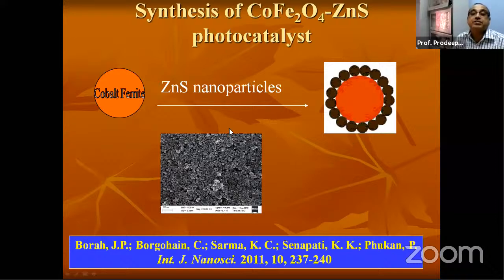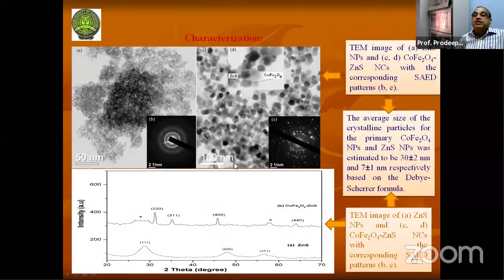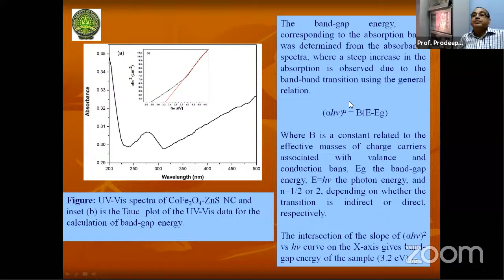Then we synthesized some zinc sulfide nanoparticles. This is the characterization, so I will not go into detail, and these are all the characterizations. Then, of course, characterization to study the band gap. Band gap energy, Eg, corresponding to the absorption band, was determined from the absorption spectra, where a steep increase in the absorption is observed. So this is a steep increase in the absorption. You can see here, this part.